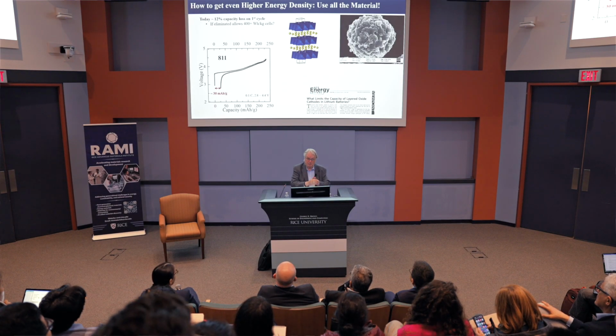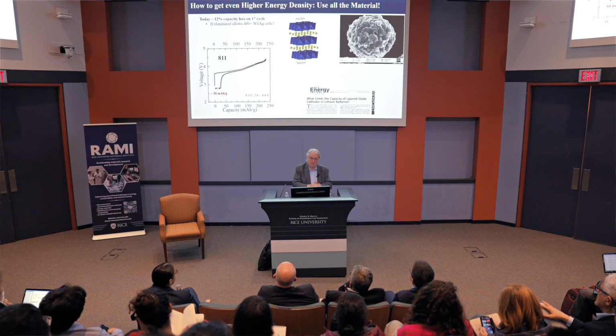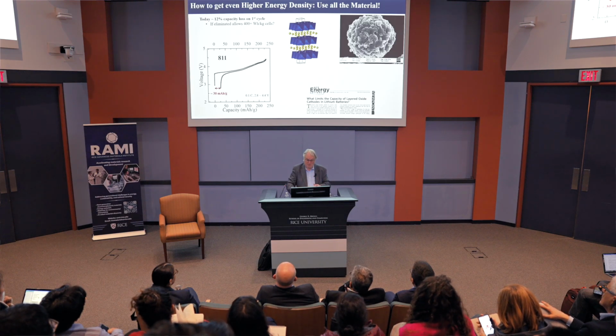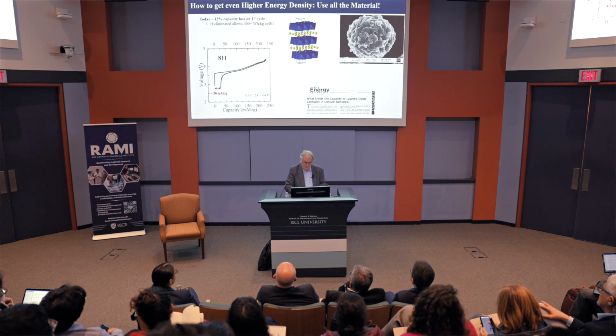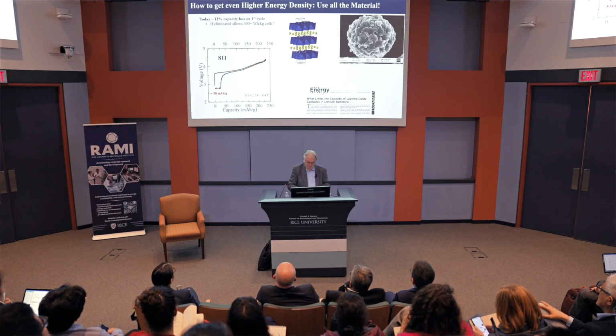And it's made worse because the diffusion mechanism is a divacancy, so you need 2 vacancies. So we're trying to overcome that, but essentially all of these materials lose between 10 and 20% of their theoretical capacity on the first cycle, and you never get it back. So we've been looking at how can we change that, how can we increase the diffusion.